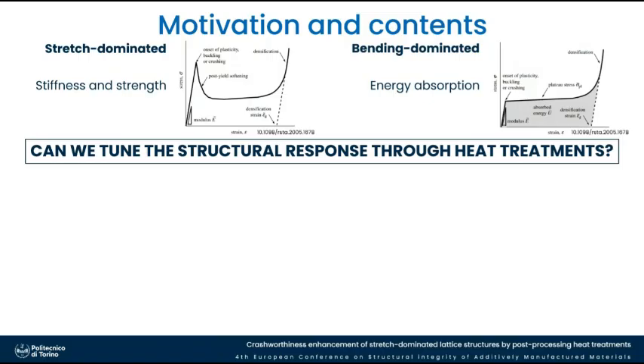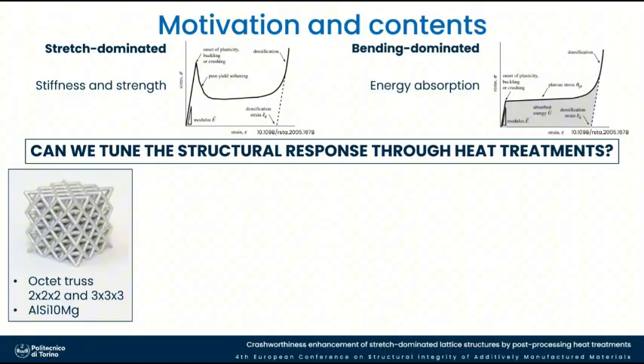So what we wanted to investigate in this study was whether we can tune the structural response through heat treatments, so if we can convert a stretch-dominated structure into a bending-dominated one. And to do that, we started from a well-known stretch-dominated structure, an octet truss, made of aluminum, silicon 10, magnesium alloy. We used specimens with 2x2 and 3x3 cell replications in the three directions.